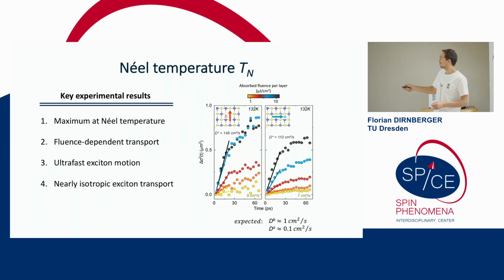Okay, so these are all fairly interesting results from our perspective because they're not expected. They're also very robust results. We've repeated these experiments with different crystals. Each of these observations is very solid. So we're trying to understand what mechanism actually drives the transport of these excitons, because clearly it's not the classical diffusion as we had expected in the beginning. Something else must be at work.